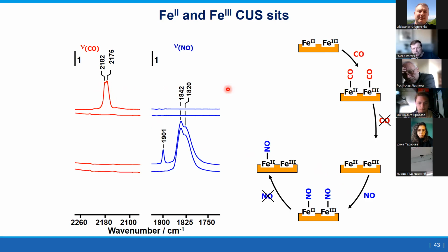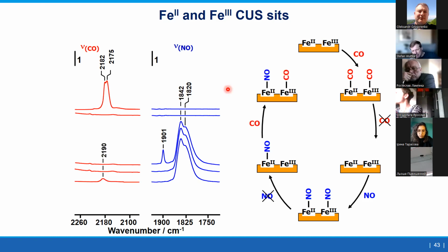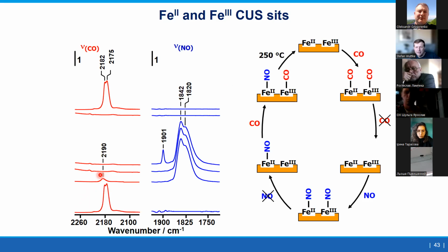And when we put argon over this again, we see that on iron 2+, the NO stays under this condition. So iron 2+ is now trapped, or poisoned, by NO. So we have only iron 3+. And when we put CO, now we can measure specifically CO on iron 3+. And then if we do activation, with high vacuum at 250 degrees, then we're removing this. And this is now a bit playing with the sample. I like this a lot, but you understand how your system reacts to the probes that you're giving, and you can use this.